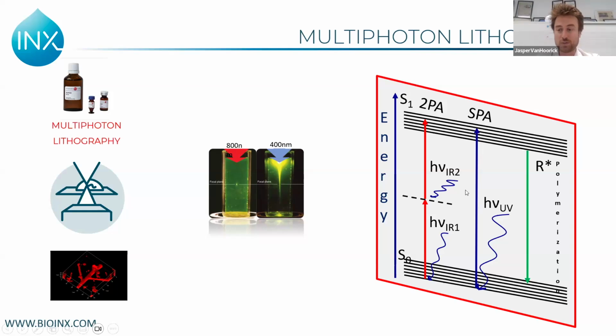And in conventional photo-induced processes, the energy of your light needs to correspond to this energy gap to which you need to excite your electron. But in two-photon polymerization, you basically use light with twice the wavelength. Twice the wavelength means half the energy, meaning that 2 photons or 3 photons, multi-photons, can surpass this energy gap. But of course, this intermediate state doesn't exist. So this means that you can only do this if you have a lot of photons, meaning that you can get simultaneous interaction of 2 photons with 1 photoinitiator molecule, which can only happen if you use high intensity and tightly focused light. And as a consequence, you will only have this in your focal spot, meaning that you will only have polymerization there, whereas in conventional light-based printing, you would have polymerization all along the beam path.